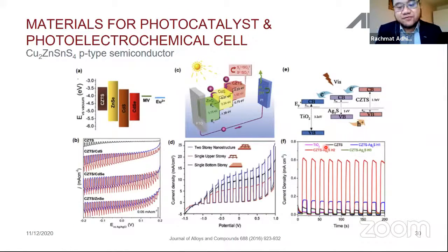I took it from a review paper, and what you see now is the band gap of different materials, what we call kesterite, copper zinc tin sulfide, or it's really long, so we always make it short as CZTS. The CZTS has a band alignment, so this is actually the band gap of CZTS, the band gap of zinc selenide, copper, cadmium sulfide, and cadmium selenide. So it aligns and it works as a photoelectrochemical cell.